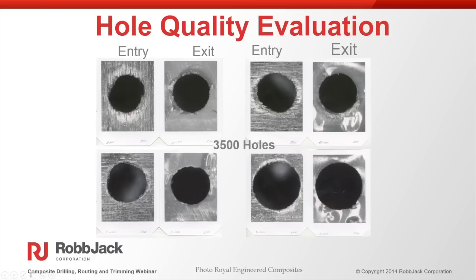And what you see on this first one here is a halo effect around the outside of the entry hole, and that halo effect is actually delaminating that adhesive layer there, and so it affects the integrity of the part. And you can see on the exit that you're getting a little bit of tear out or uncut fibers, and you don't really get that clean cut. And you have a variation of all that.